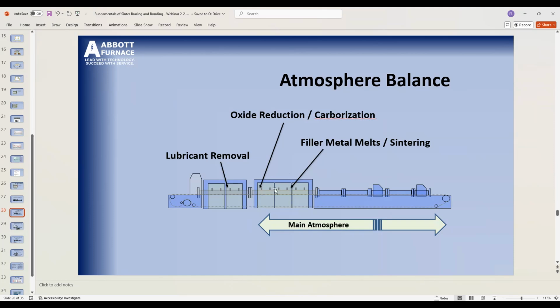But you notice in normal brazing, we would heat up, hit the melting point of the filler metal. We'd stay there between 2 to 5 minutes and cool off. Here, we're going to heat up to our sintering temperature. Everything's going to melt, but we're going to sit there for 20 to 30 minutes. So there's all the time in the world for that part to steal that filler metal. That's why it's so important for us to control that cleanliness of those pores and control that density so that we don't steal all the filler metal from the gap and not join our parts.